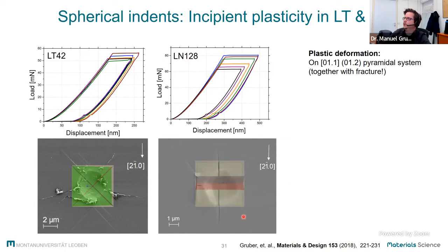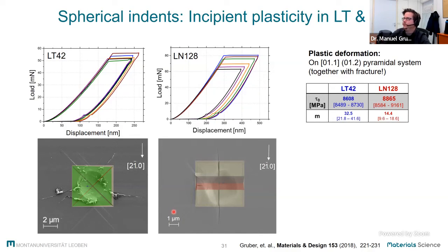And we could see that especially this kind of pyramidal system seems to be the origin of twinning in these materials, if we have stress states in small scale experiments like we see here. Interestingly, the first plastic deformation is at more or less the same shear stresses for both materials.